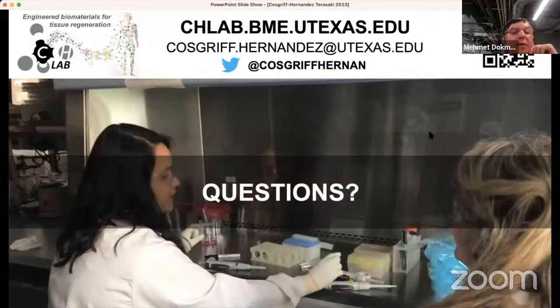Thank you for the talk, Professor Hernandez. A question came in: I'm a polymer chemist and curious to know the cross-linking mechanism and the reaction conditions. So this is standard radical cross-linking — the iron gluconate is causing the decomposition of the ammonium persulfate, and then that radical cross-linking is initiating the acrylamide end groups of the polyether urethane diacrylamide. These were all done starting at room temperature, but then did all the cross-linking and kinetics at 37°C to mimic in vivo conditions.